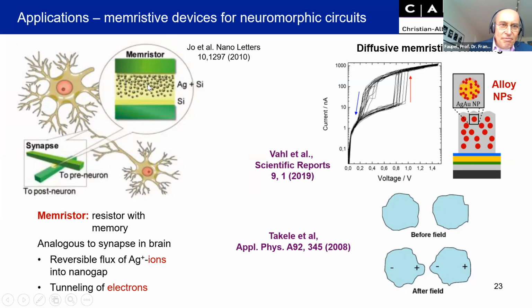At the high fields between the nanoparticles, ions are released from silver. The ions move into the gap here, and the more current flows, the more silver nucleates in the gap, and this gradually decreases the resistivity. And if you switch the electrical field off, you have a memory. And if you take the reverse polarization, you can dissolve the silver again. And so you have a reversible change in resistivity.